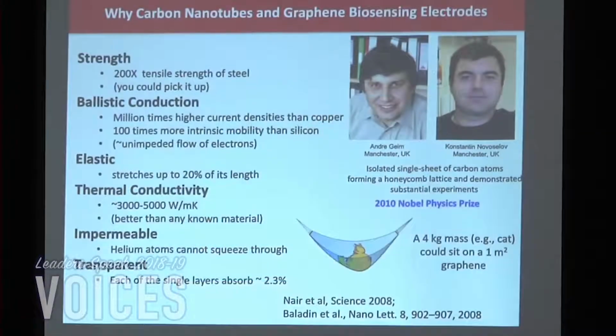So with that said, let's go into some of the materials we're using, such as graphene. Why use this material? There was a Nobel Physics Prize in 2010 for isolating a single monolayer of graphite, or graphene, and understanding its material properties, and that's what those physicists did. We found out that it's incredibly strong. It has 200 times the tensile strength of steel. It has ballistic conduction, with million times higher current densities than copper, for example.